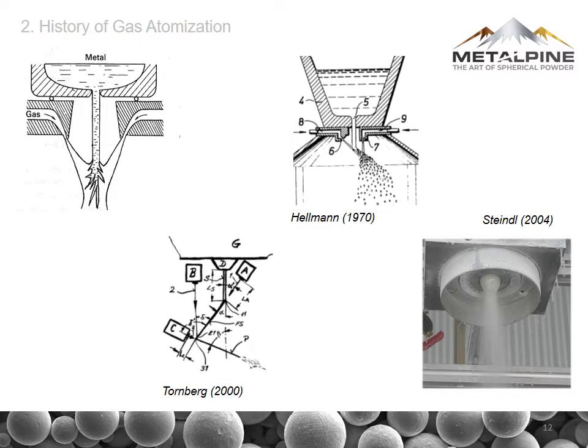Quite commonly used is also the open jet atomizer. You can see here the metal flowing through a hole downstream, and the circumferential gas stream. The metal is building an open jet, and it has got lots of possibilities to escape from the gas stream. So the drawback of the system is that the particles at the end will be coarser and have a quite wide particle size distribution. The advantage is, of course, that it's much easier to operate, as you don't have any issues with nozzle tip freezing and stuff like that.